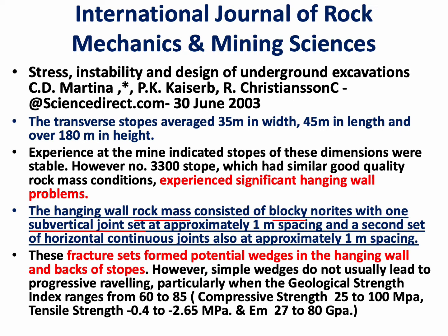The hanging wall rock mass consisted of blocky norites, with one subvertical joint set at approximately 1 meter spacing, and a second set of horizontal continuous joints also at approximately 1 meter spacing. These fracture sets formed potential wedges in the hanging wall and backs of stopes. However, simple wedges do not usually lead to progressive raveling. There could be singled out failures of wedges, but simple wedges do not usually lead to progressive raveling, particularly when the geological strength index, as in this stope's case, ranged from 60 to 85.